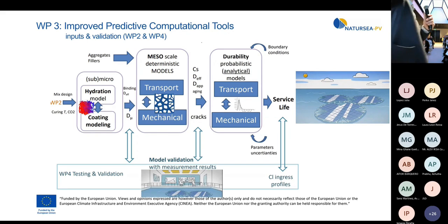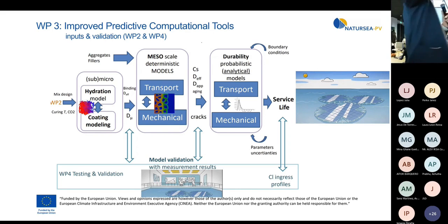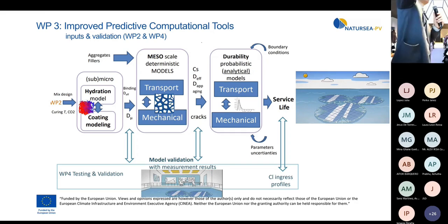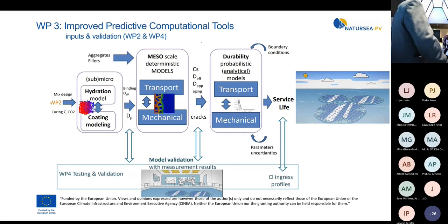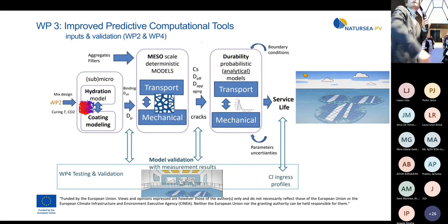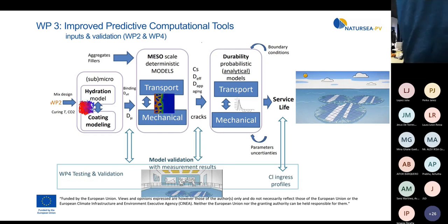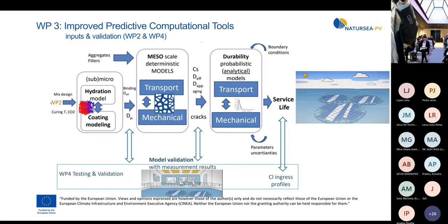So first, here we do the base, the binder, for the micro level, let's say. And for this, we have two tasks on hydration modeling and coating modeling to see how the coating also interferes with the concrete. And then this is the meso scale. So we need to explicitly model the aggregates and ITZs, the interfacial transition zones, the preferential pathways that the chlorides take. But for this we need input for the diffusivity of the binder. And here we have the output diffusivity of the mortar, and this should be tested. And that way we can validate and calibrate our models.